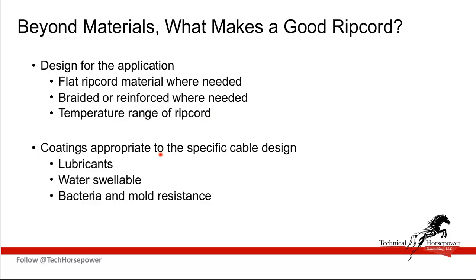And, of course, the other side of this, there are coatings that are appropriate now for these ripcords. In some cases, the material that's used as a lubricant is almost like a wax to help yarns tear through steel armor and not destroy themselves in the process. In other cases, one of the other problems is the cables have to not let water pass, so they have to have a water-swellable component.